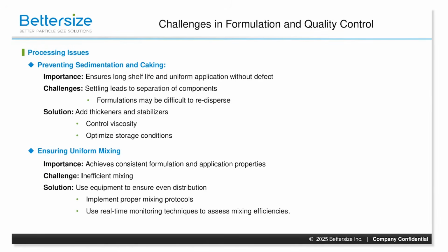In terms of processing issues, the goal is to prevent sedimentation and caking. This will ensure long shelf life and uniform application. The challenge is that particles can settle over time, leading to a separation of the components. And high viscosity formulations may be prone to caking, forming hard lumps that are difficult to redisperse. So solutions include using thickeners and stabilizers to maintain the suspension and prevent sedimentation. Controlling viscosity ensures a smooth flowing consistency, and optimizing storage conditions such as temperature and humidity reduces the risk of caking.